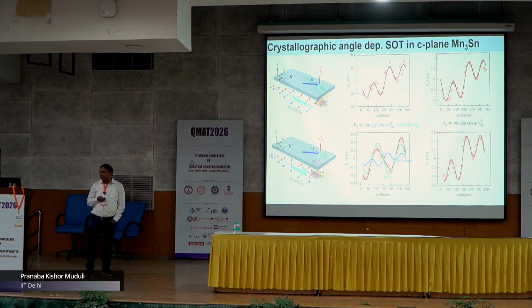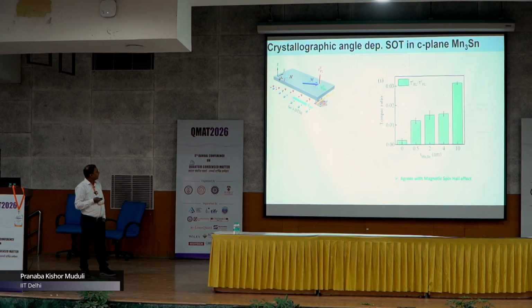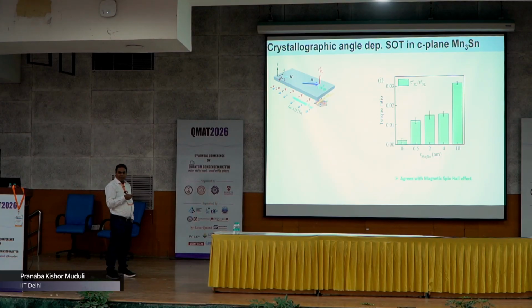This is very much consistent with the magnetic spin Hall effect, and furthermore, the magnetic spin Hall effect is a bulk effect. So we expect that it will change, and increase, as you change the thickness of Mn3Sn. So this is what we also see. This is the ratio of the out-of-plane torque with respect to the in-plane torque, and we see that it is increasing, and this agrees well with the magnetic spin Hall effect. Because if it was spin-stopping, we expect that it would be constant, because the interface effect will not change with the thickness of Mn3Sn.